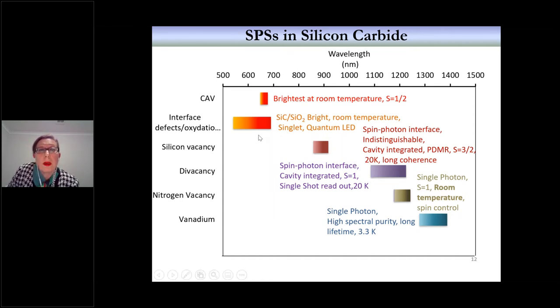So in this slide, you can see various color centers in silicon carbide. They have been identified as single photon emitters and, some of them, also as a spin photon interface. The visible ones are not spin photon interfaces, but are very bright emitters. Then we have emission of, for instance, the silicon vacancy, which is in the region of 900 nanometer, and the divacancy, around 1,000 nanometer, the V center in silicon carbide at 1,200 nanometer, and the vanadium impurity in silicon carbide at around 1,300 nanometer.